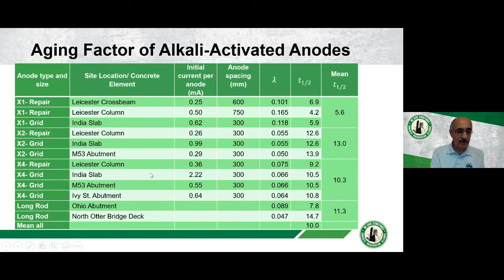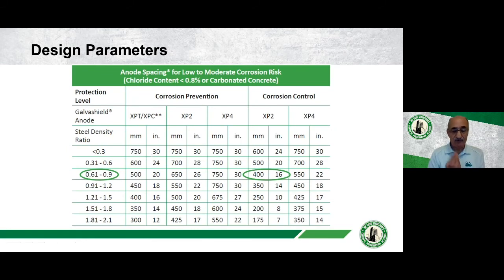So how can we then use this information? It's very, very useful information. So there's two parameters. There's an initial current that we know that our anodes can deliver, and there's the half-life, or the aging factor. So I'll give an example of how we've been traditionally designing. The set of tables that we provide, and if we're looking for a less than 0.8% chloride, and we want to achieve corrosion control, but we're using XP2 anodes, or the equivalent CC2s. Our table tells us that for a steel density of, I've taken it as 0.61, we need a spacing of 400 millimeters, or 16 inches.